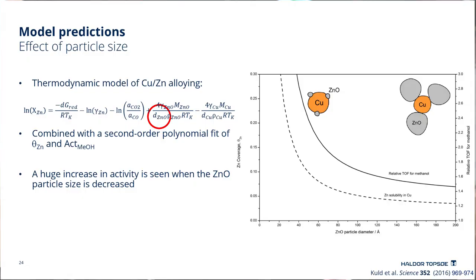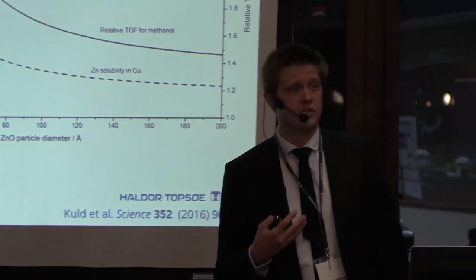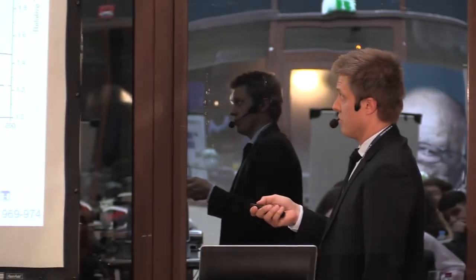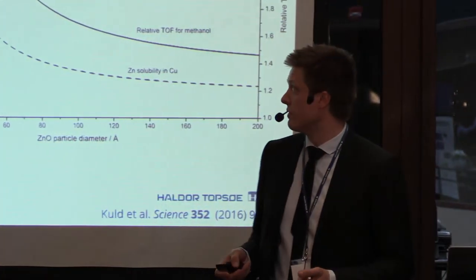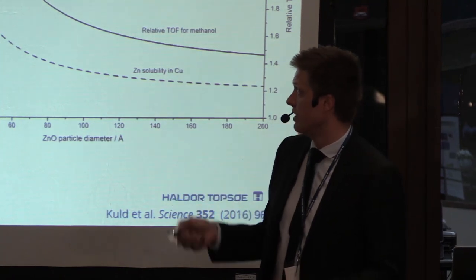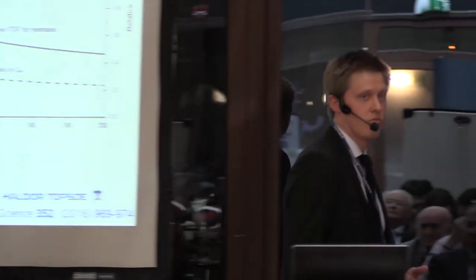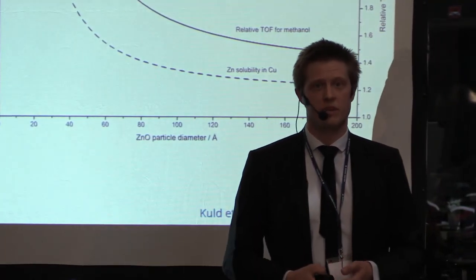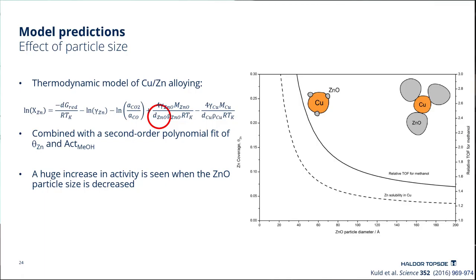So we can go one step back. If you recall this thermodynamic model, it did not only contain a term with the CO and CO2 ratio, but also some of the physical characteristics of the catalyst system, like the zinc oxide particle size. So we can do some exciting stuff now. We can combine this model with a second order polynomial fit of the relationship between the zinc coverage and the methanol activity. And then we can try to predict how the methanol activity will be impacted by changing some of these fundamental characteristics. So this is what is shown here.